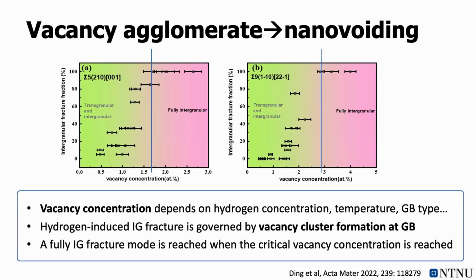So what we can do here is run a lot of simulations with different hydrogen concentrations at different temperatures, and then monitor how the vacancy concentration relates to whether transgranular, intergranular, or mixed mode fracture happens, to obtain this full map of the intergranular fracture of hydrogen in nickel. And you can see here very clearly that this hydrogen-induced intergranular fracture map changes with the grain boundary type. For different types of grain boundary, we have a different critical vacancy concentration for the transition of the fracture mode.